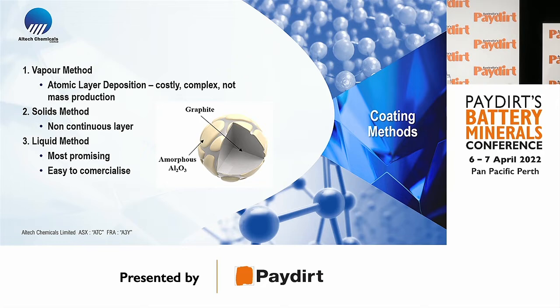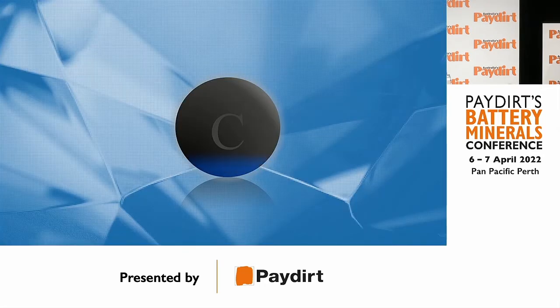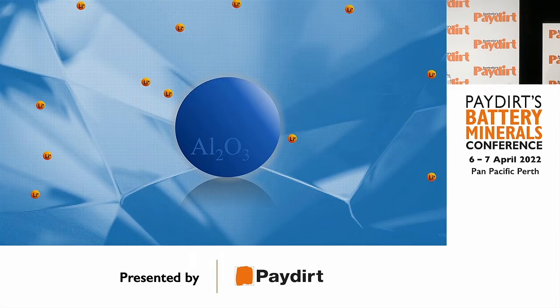So there are three methods of putting alumina onto graphite material or silicon material. The vapor method, called atomic layer deposition, the solid method, and a liquid method. Our process is actually a liquid method. And we have the technology to put a very fine layer of alumina around graphite and silicon. It's a 2 nanometer layer. And what that does is prevent the SEI layer from forming. The beauty of this layer is that it doesn't stop the performance of the battery. So lithium can go through the alumina layer.